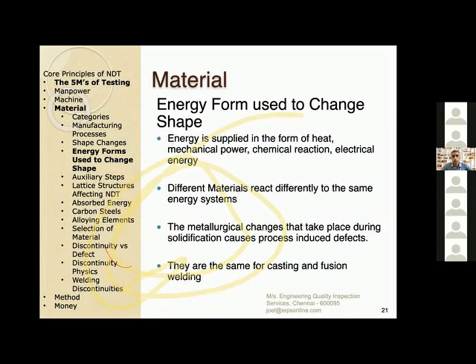So what basically happens is when I use an energy form to change the shape, the metallurgical properties change. And in this particular case, not just this particular case, any case for that matter, all these processes invoke a defect in one way or the other. So in a typical case where heat treatment is done, we see a lot of surface cracks coming out from the component once it's heat treated. So the overall benefit is achieved that the metal is taken above the Curie temperature, the surface is hardened and everything.